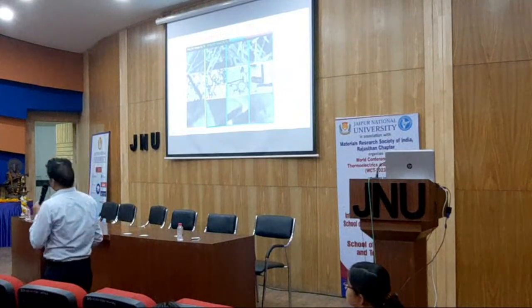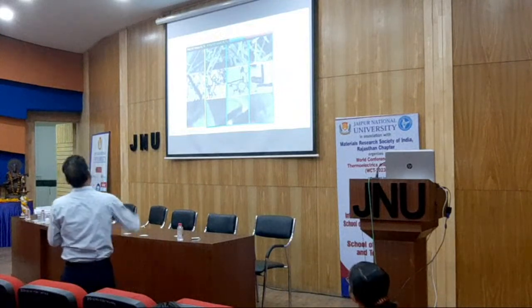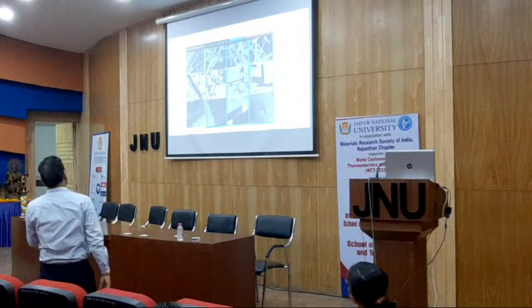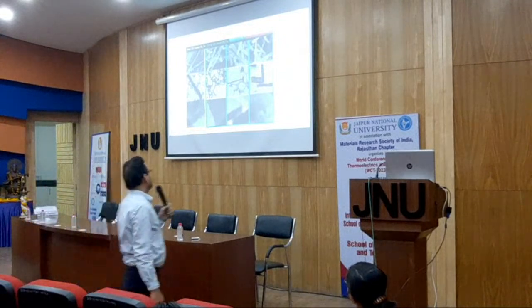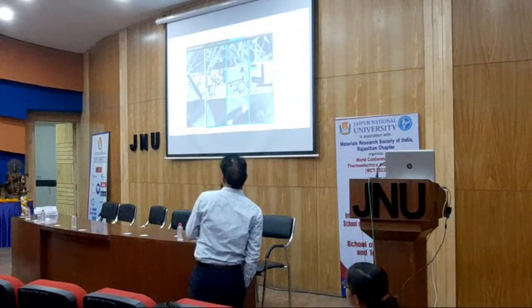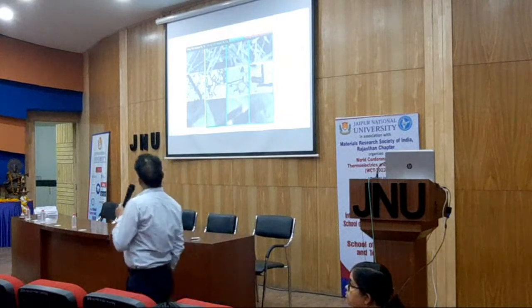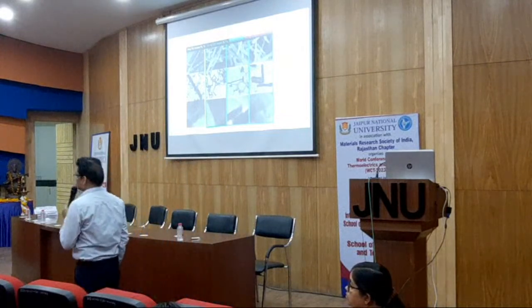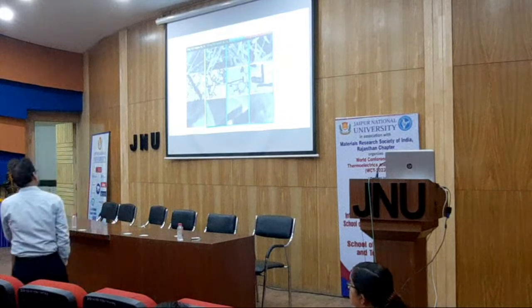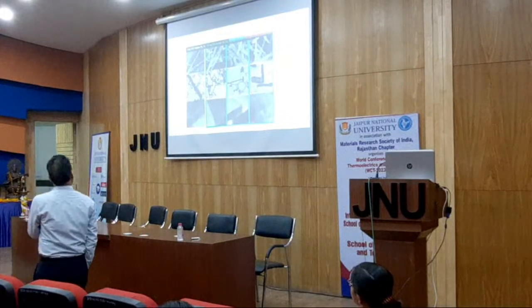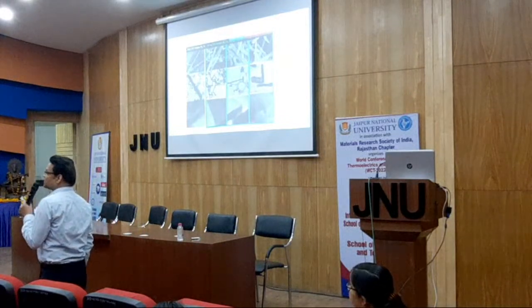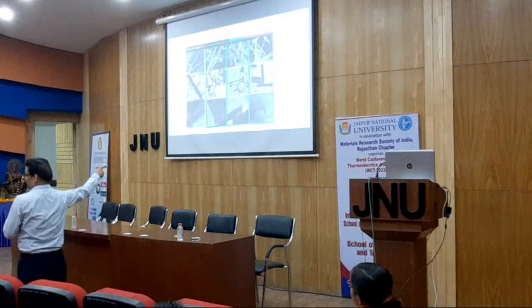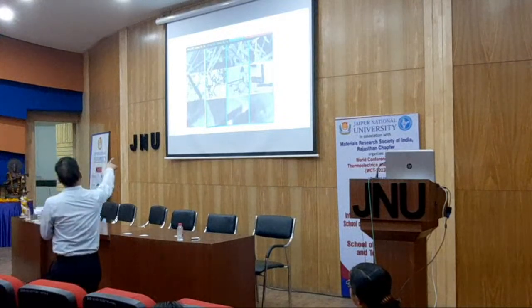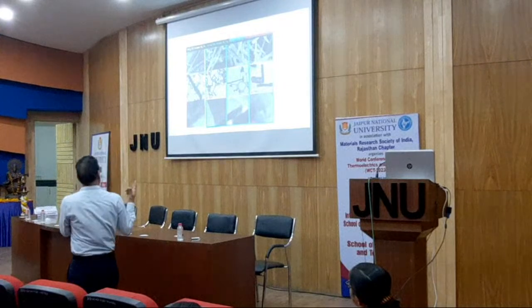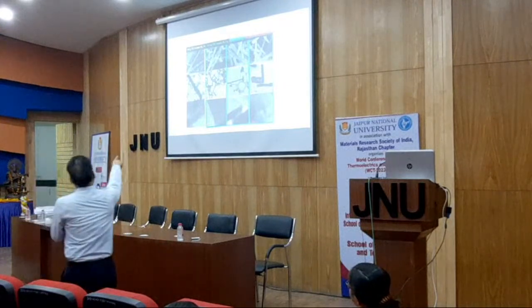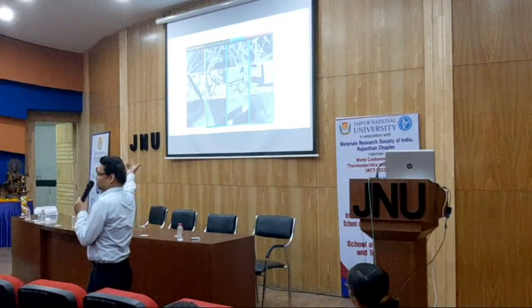Sir, in that high resolution transmission, that last one is TEM, HRTEM. Sir, are you establishing any graphene oxide in that bismuth telluride? What the HRTEM is indicating is that putting graphene oxide and reduced graphene oxide is creating a lot of disorderness. So if you see the disorderness in graphene oxide is very high as compared to reduced graphene oxide, and this is making some percent amorphous structure also, right?